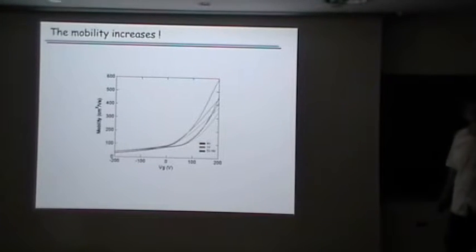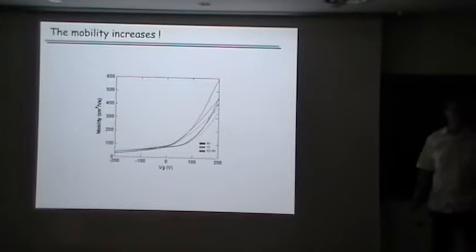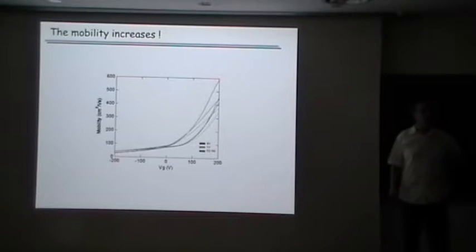At the same time, if you measure the mobility again at low field, in this region here in the negative voltage, when you remove electrons to 0, it's something very smooth, and then it rises up by a factor of 10 when you put more electrons.